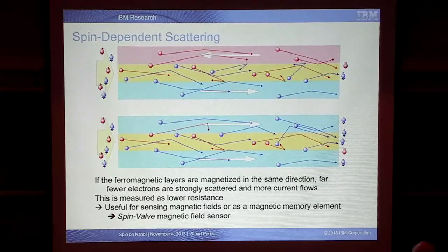So we apply a magnetic field. The magnetic field, for example, would change the magnetic orientation of this red layer, so it's along the magnetic field, and we will lower the resistance of the structure. I'm sorry, when you change that layer from red to blue, yeah. So you're not changing the material, you're changing. That's right. You're changing an applied field.